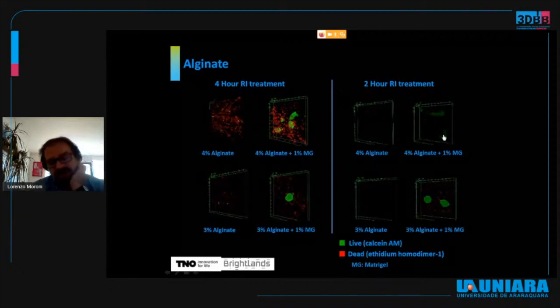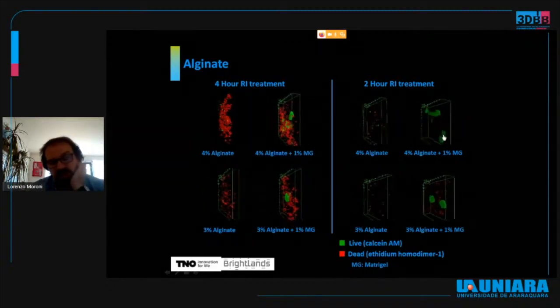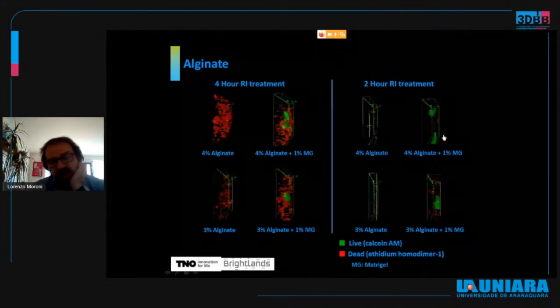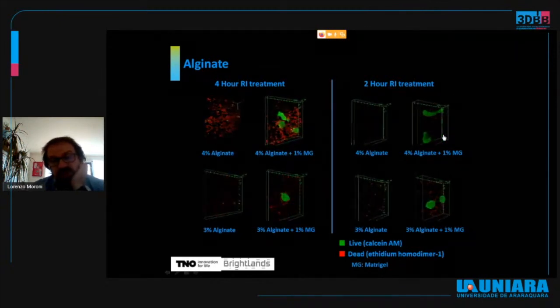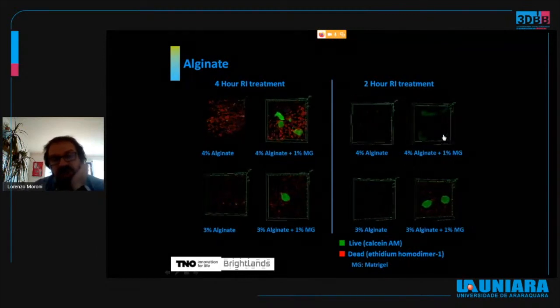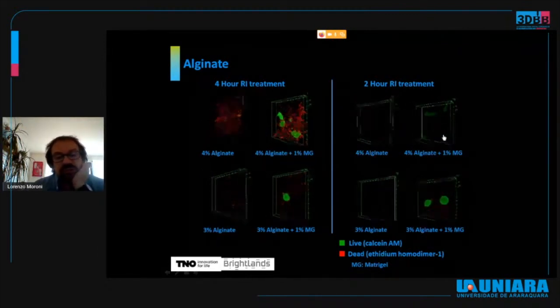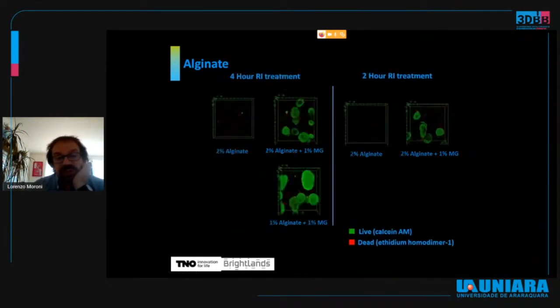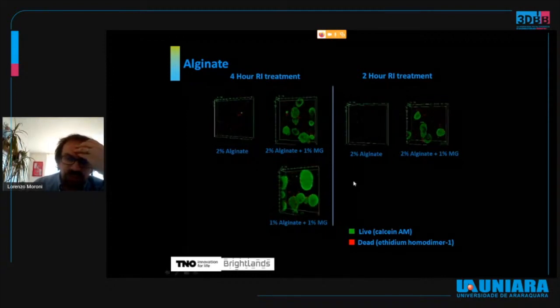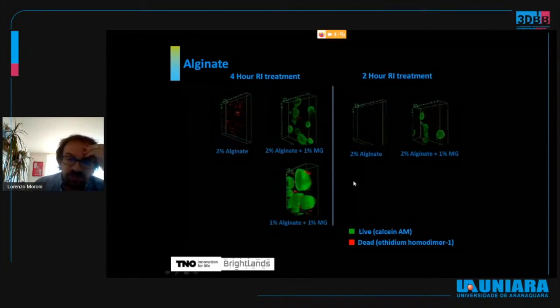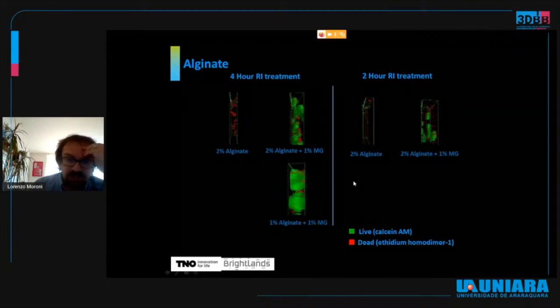Another way to further increase the viability of the cells is to look at methods where a lower concentration of gel could be used. Again, here you see that by using simply alginate and reducing the concentration from 4% down to 2% or even 1% alginate with 1% of Matrigel, sorry, it was possible to obtain much more satisfactory viability of these organoids after bioprinting.